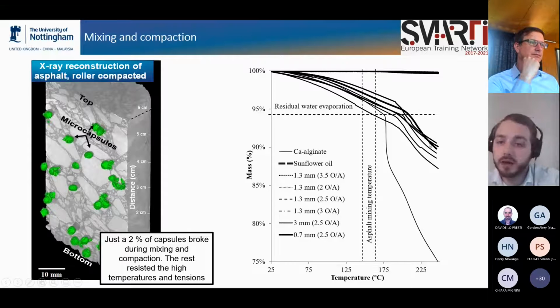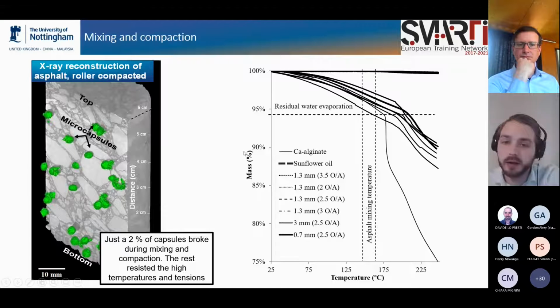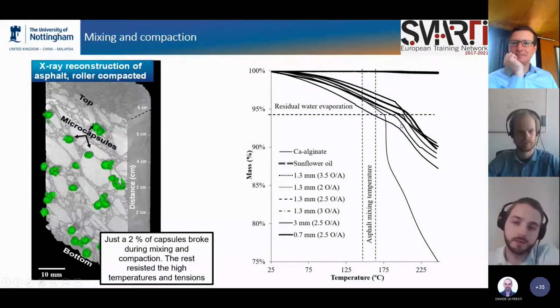Also, during the thermogravimetric study, we got this graph. It represents the loss of mass when the temperature is increased, and we can see that we have a loss of mass at the asphalt mixing temperature, but we also need to consider that the capsules have some humidity, so we related this loss of mass to the evaporation of residual water.